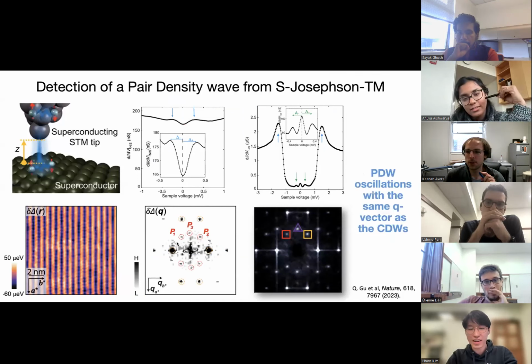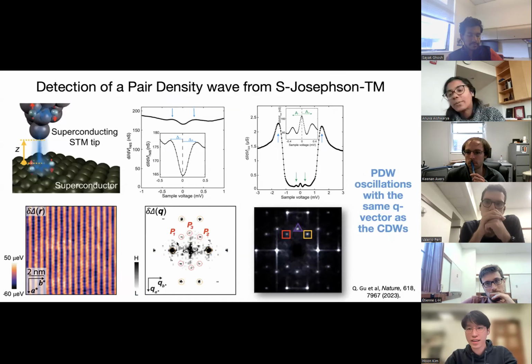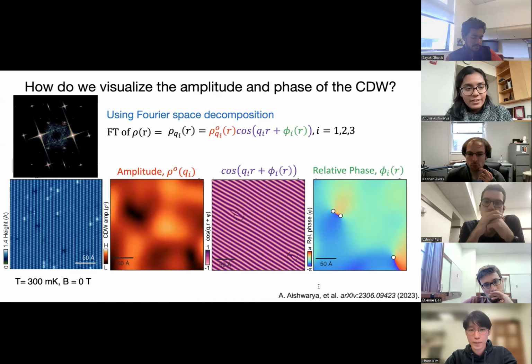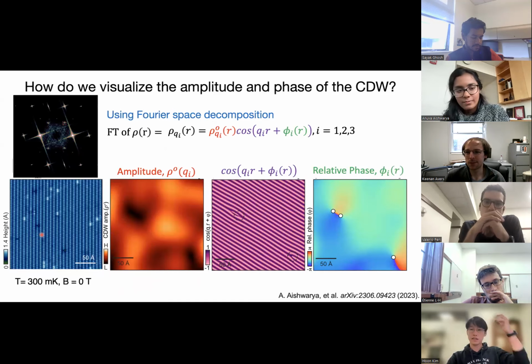My question was, what are the reasons you think you are observing charge density wave, but not pair density wave? Because we are at very high energies, much higher than the superconducting energy scale. The superconductivity gap is plus minus 250 micro eV. And this topography, for example, is at minus 20 meV. I see. So like two orders of magnitude difference. Yes. All right. Thank you.